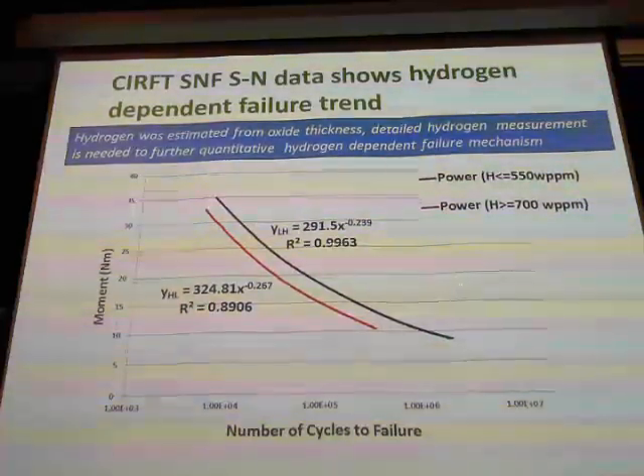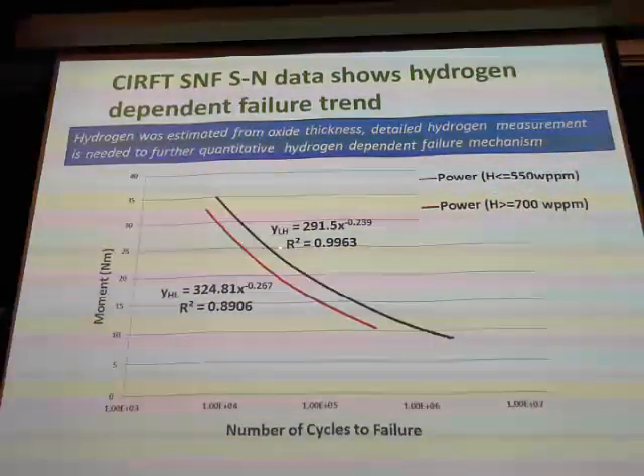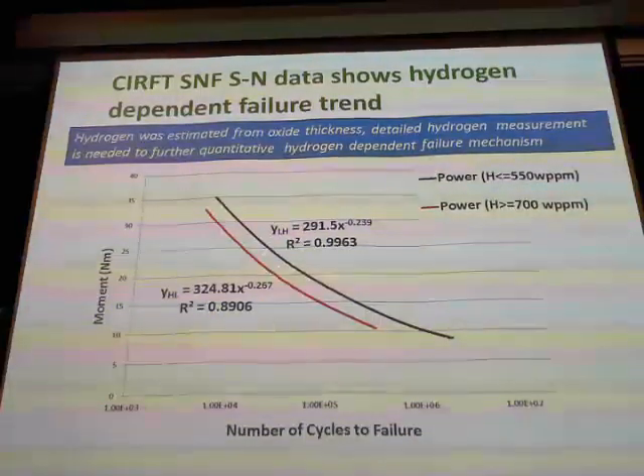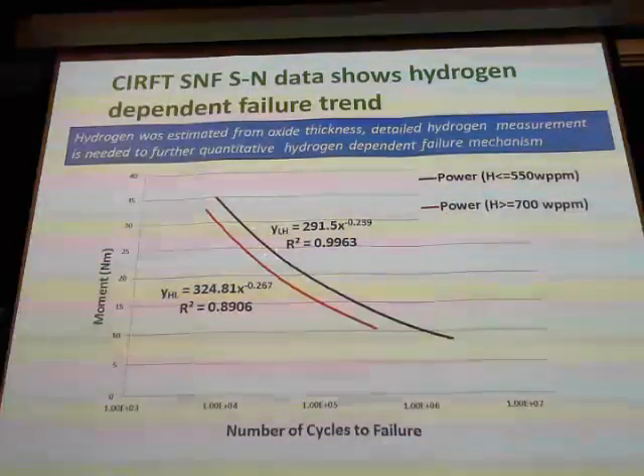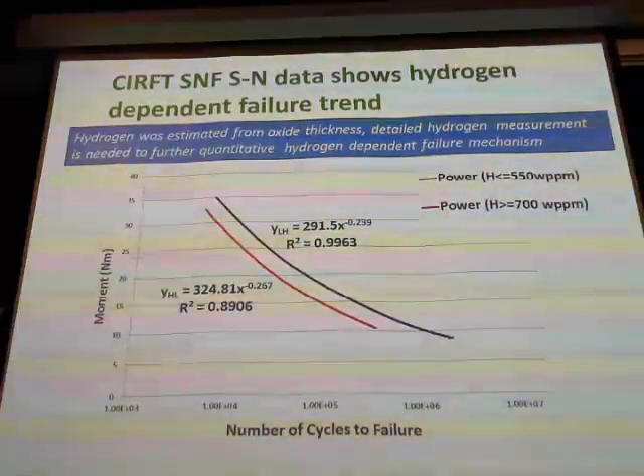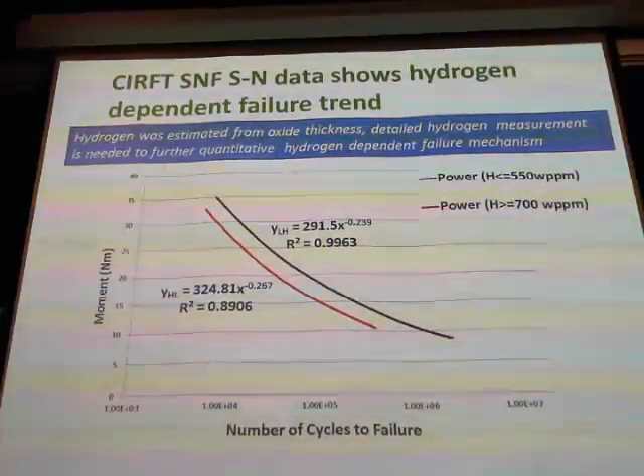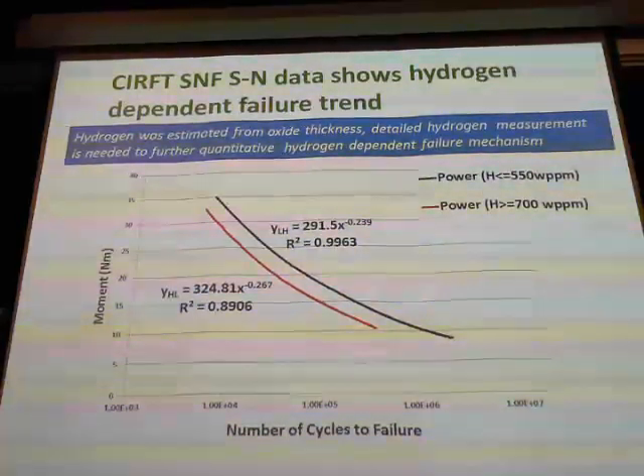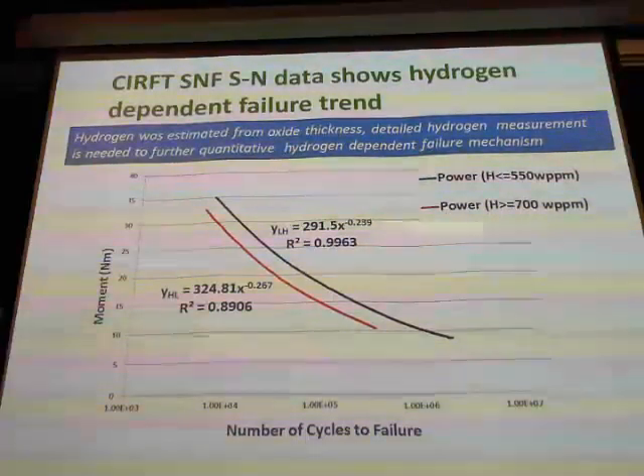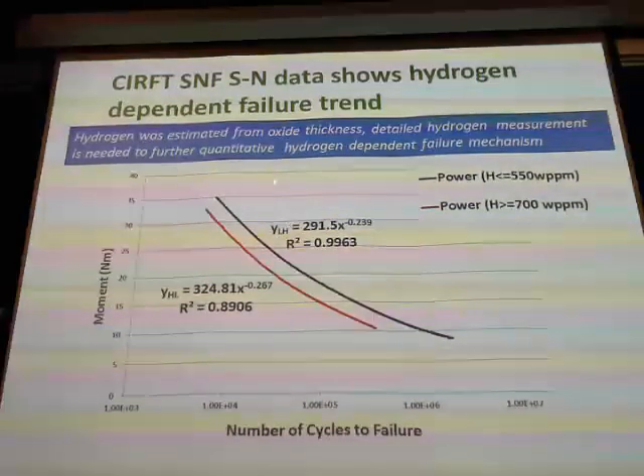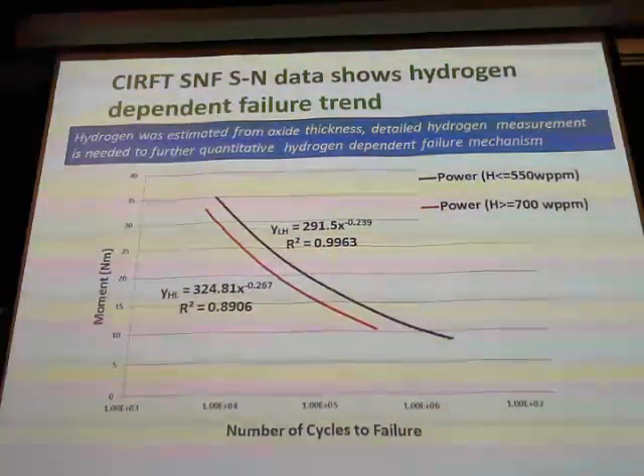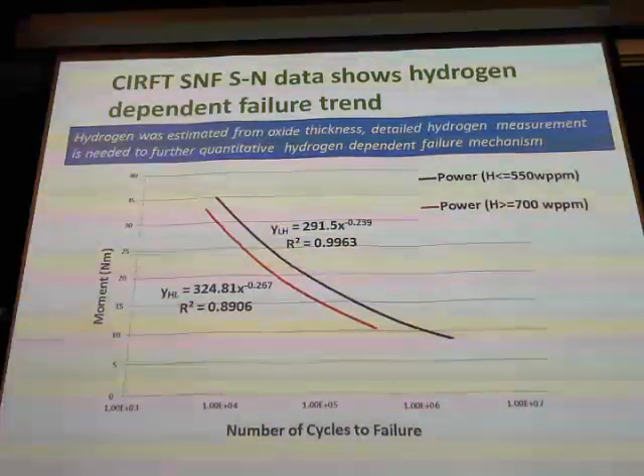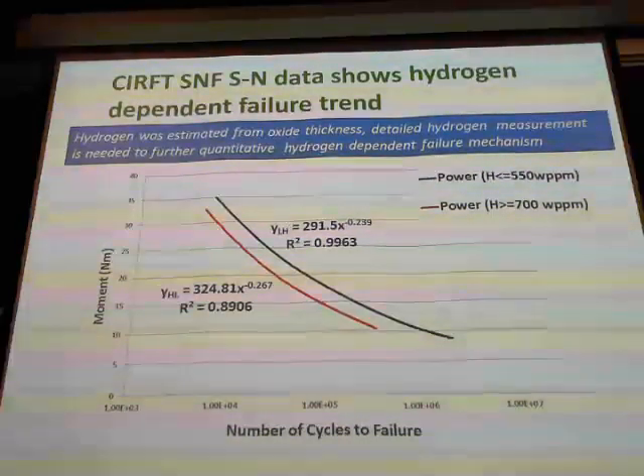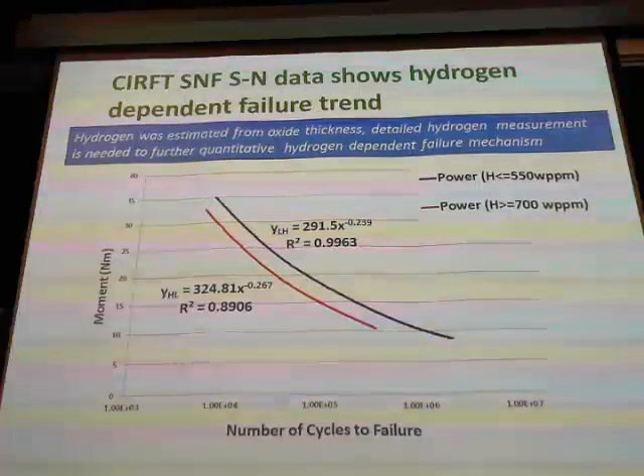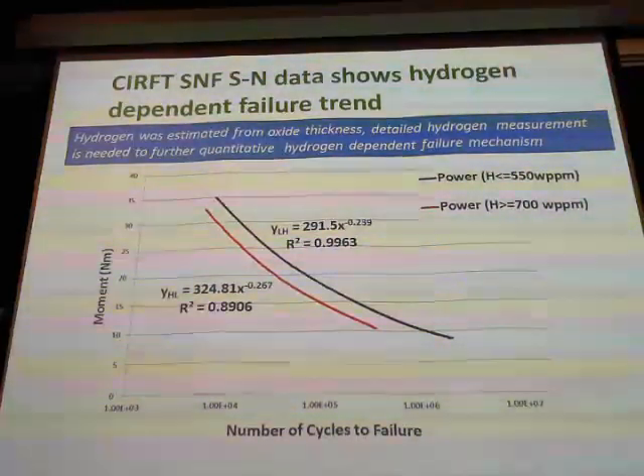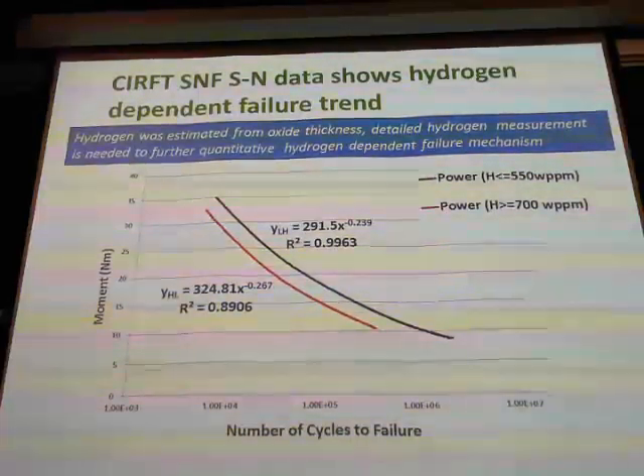This one here is hydrogen below 550 and above 700 ppm, and you can see a shift. This plot is generated by dividing into two different groups, hydrogen or hydride. You estimated this from the thickness of the oxide layer on the outside, assuming that all the hydrogen that went with that oxygen is in it. This data I got from Mike Ballone. He measured the oxide surface and compared the oxide with the hydrogen in it. That's right. The hydrogen measurement is a very difficult test. So the consensus is that oxide thickness is more uniform.